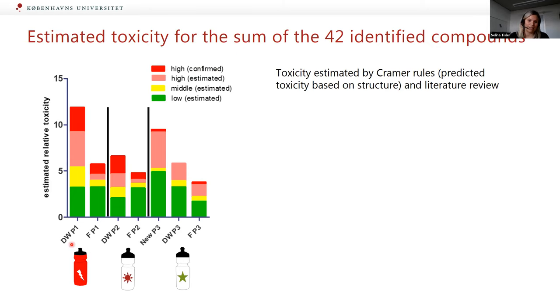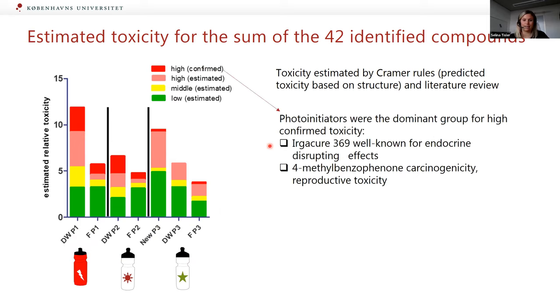And here we see always dishwasher and after additional flushing for the different bottles. We see that all bottles had the highest toxicity after the dishwasher process, and that the red bottle had the highest confirmed toxicity. For this confirmed toxicity, mostly photoinitiators were the dominant group. For example, Irgacure 369 and 4-methylbenzophenone, where toxic effects are known.